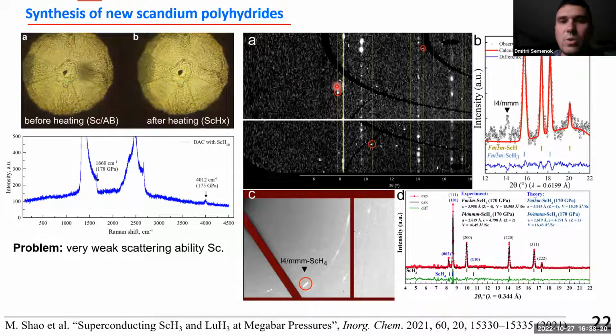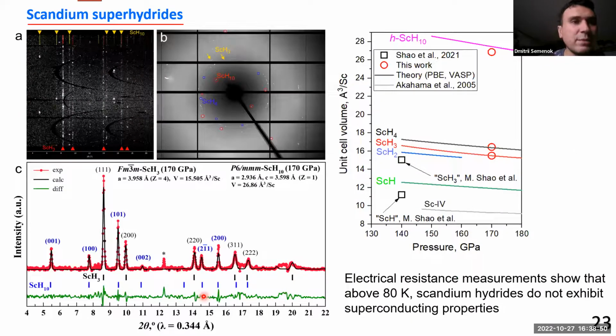We see quite weak diffraction reflections, single-crystal-like diffraction reflections, only three, maybe, spots, just a few spots. But the circle is quite strong. When we look at the diffraction image, we see that the signal is quite obvious. So we think that we synthesized this tetragonal scandium H4. And the second pattern was much more interesting.